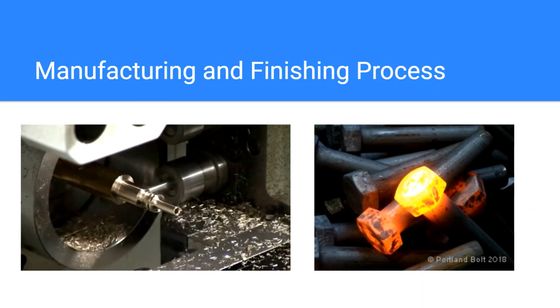A 431 stainless steel bolt could be made using the same process as a plain carbon steel bolt. 431 stainless is possible to hot work. The head could be formed by heating using an induction furnace to between 1150 and 1200 degrees Celsius and forging into the correct shape using dies. 431 stainless can air harden to a degree, which could make cutting threads after forging more difficult. However, if the heat is localized in the head, the area where the threads are cut wouldn't be affected.